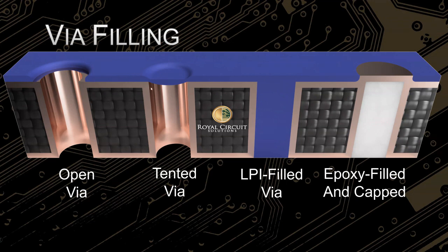And how big can you tent? I mean, what via diameter hole can you actually tent? We can tent anything up to 50 mils. All right. After that, it's just going to fall apart. Yeah, or it becomes unreliable.